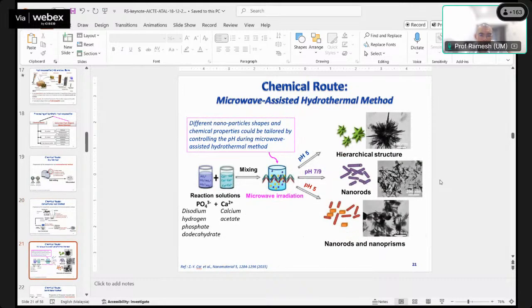All right, then there's also the microwave assisted hydrothermal method. Researchers have used, instead of a normal hot plate, a machine with the ability to induce microwave. Microwave allows the reaction to take place when you have the calcium based liquid solution mixed with the phosphate based solution, and you pass it through microwave, so you heat up the liquid, and that causes the reaction to take place, and subsequently you get different products depending on pH. You need to control the environment, and most of the time it is the pH that we can control. For different pH you get different morphology of HA crystals being formed. All right, so pH 5 is typically reported in the literature. I've not done the microwave assisted hydrothermal method.